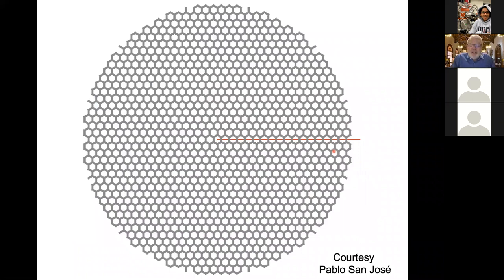But the Moiré materials we have in mind are related to a specific type of Moiré pattern. It's the Moiré pattern created by overlaying two similar two-dimensional crystals. And you're looking at an example of a Moiré superlattice, or you're actually looking at a bilayer two-dimensional crystal system. It's the simplest type of Moiré pattern. And this is actually a picture of two honeycomb lattices, one on top of another, represented by these gray lines that connect the lattice points. And you only see one of the two-dimensional crystals because they're sitting right on top of each other.